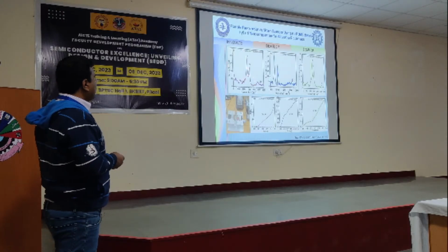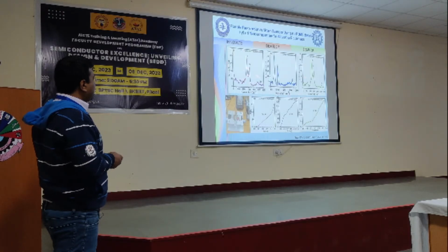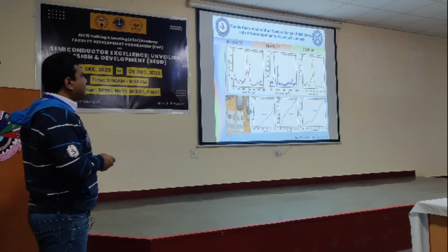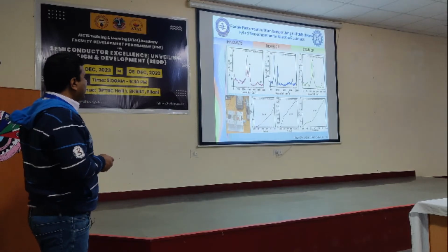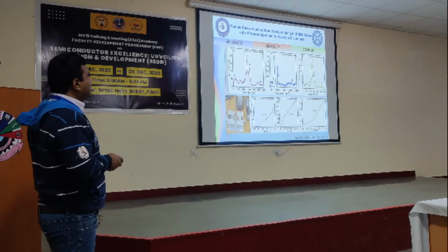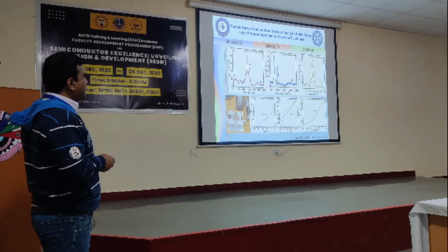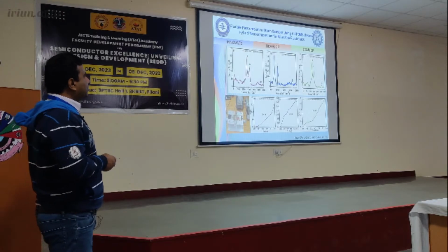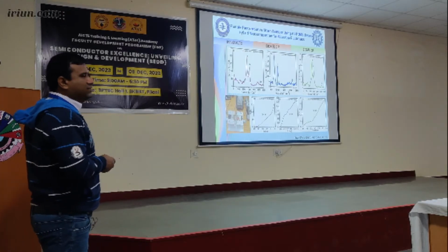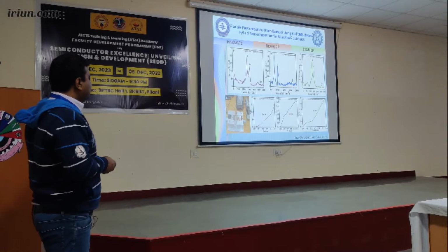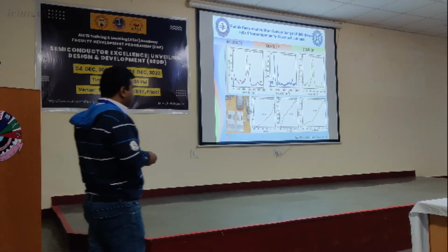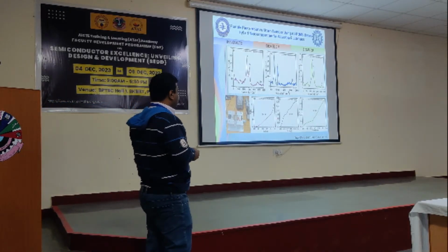And this one is your Raman spectroscopy measurement for all the cases, for material confirmation as well. D, G and 2D bands: in all the cases he found D, G and 2D bands. Because of the appearance of these peaks, you can ensure that the formation of graphene and GNP is taking place here. Now this is your device fabrication and device testing.